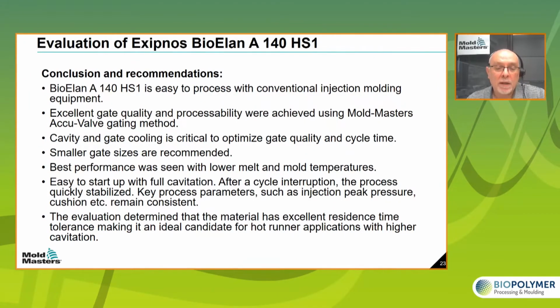We found it easy to start up. We would achieve full cavitation on our first shot. After a cycle interruption, the process was quickly stabilized, and key process parameters such as injection peak pressure, cushion, etc., remained consistent. The evaluation determined that this material has excellent residence time tolerance, making it an ideal candidate for hot runner applications with higher cavitation.